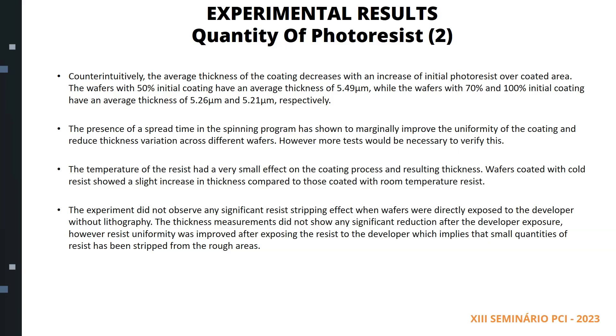The presence of a spread time in the spinning program has shown to marginally improve the uniformity of the coating and reduce thickness variation across different wafers. However, more tests would be necessary to verify this. The temperature of the resist had a very small effect on the coating process and resulting thickness; wafers coated with cold resist showed a slight increase in thickness compared to those coated with room temperature resist. The experiment did not observe any significant resist stripping effect when wafers were directly exposed to the developer without lithography. However, resist uniformity was improved after exposing the resist to the developer, which implies that small quantities of resist had been stripped from the rough areas.